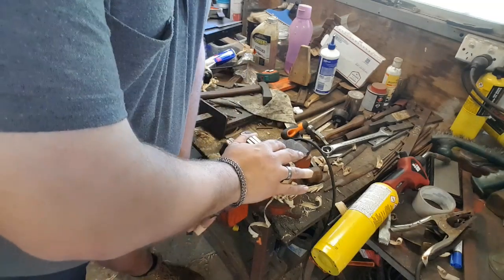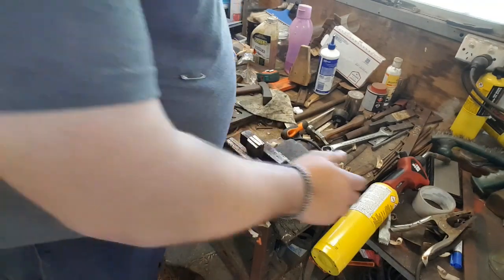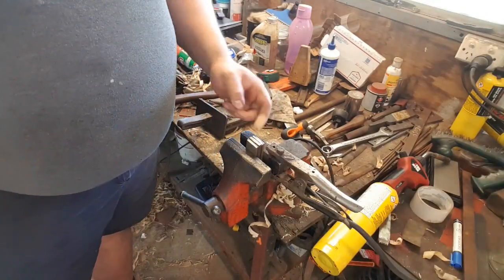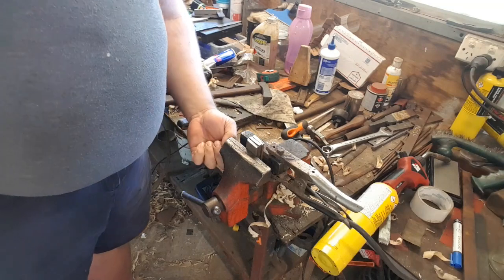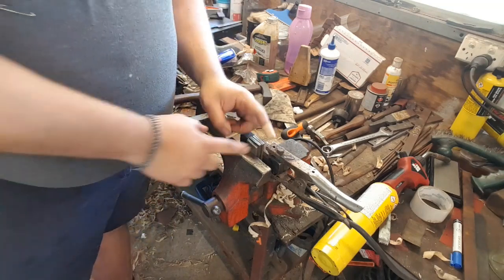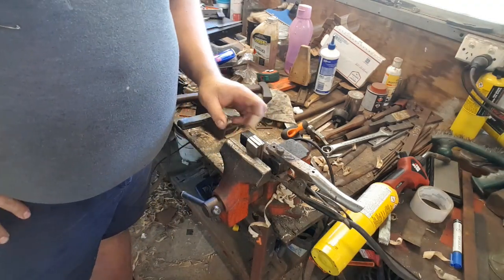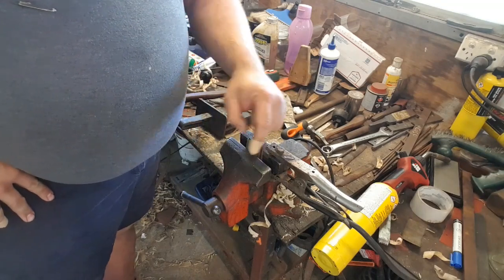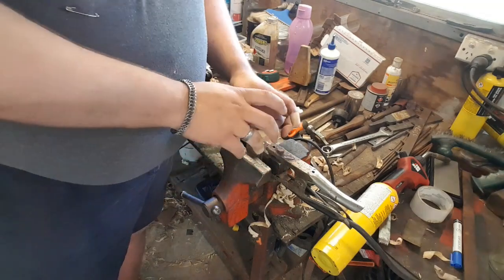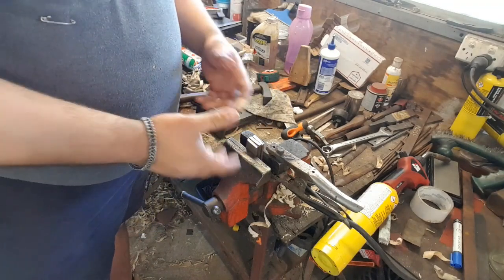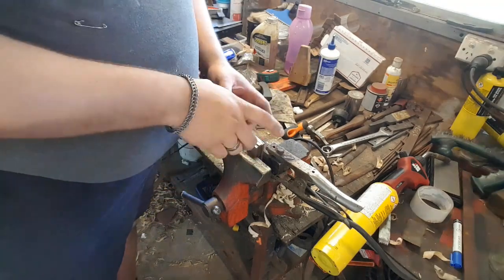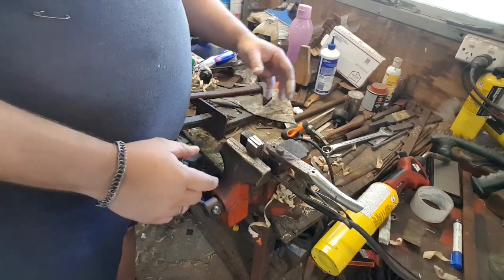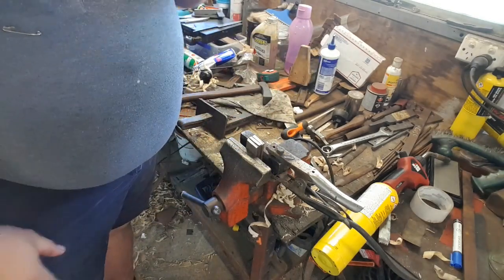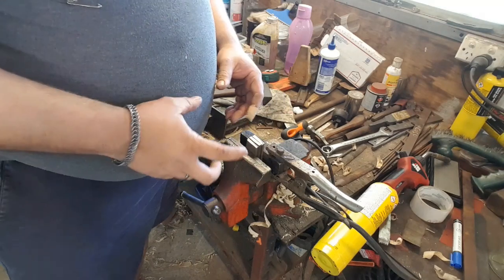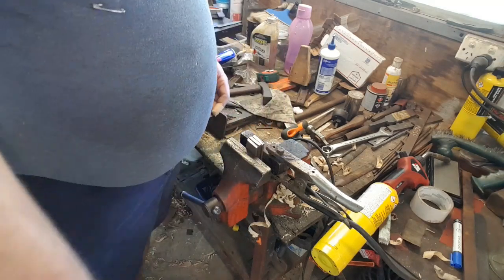So now that it's clamped, and clamped as hard as we possibly can, we're going to fire up the welder, and I'm going to run a bead down both sides, one at the front end and one at the back end. And then if this was a longer billet or a slightly taller billet, I would also run one up each side, or potentially two, depending on how large the billet is. These are very small billets for demonstrative purposes. But the larger the billet, the more you want it consolidated and welded up as hard as you possibly can, because you don't want that expansion happening and opening up all your gaps.